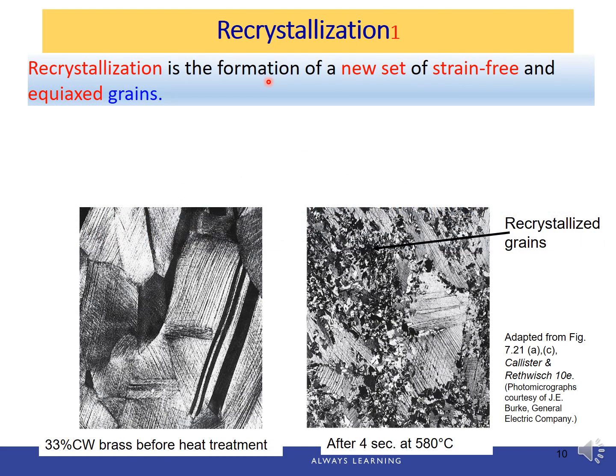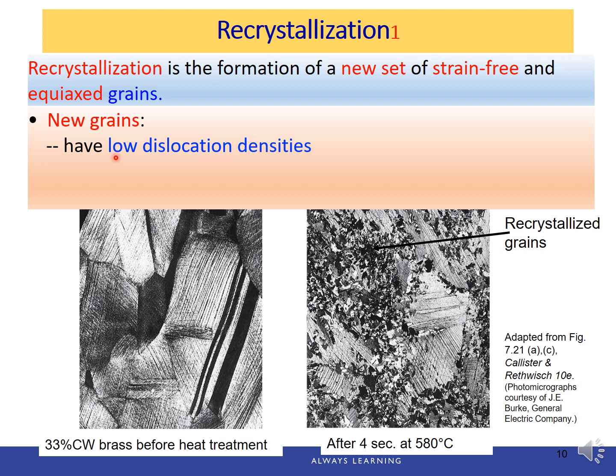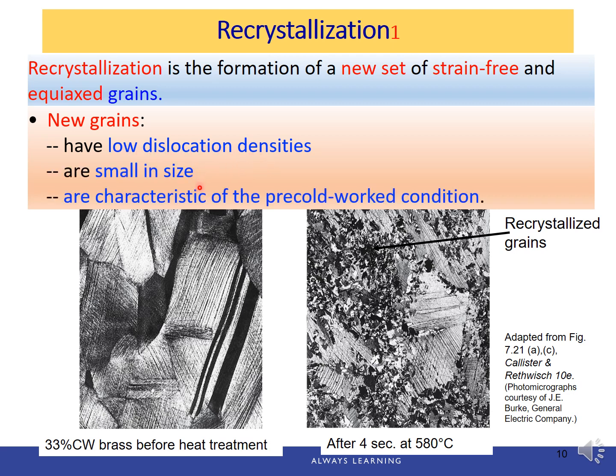Next stage, if we increase the temperature during the heat treatment, is called recrystallization. It is the formation of a new set of strain-free and equiaxed grains. Again, that means the grains have approximately equal dimensions in all directions. And those new grains have low dislocation densities. They are small in size and also are characteristic of the pre-cold worked condition.